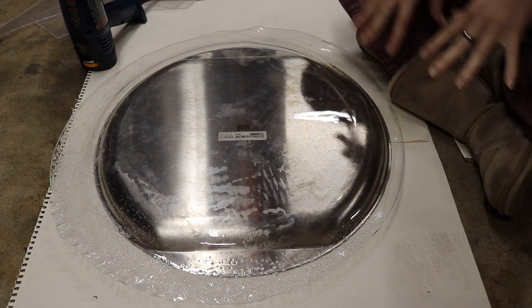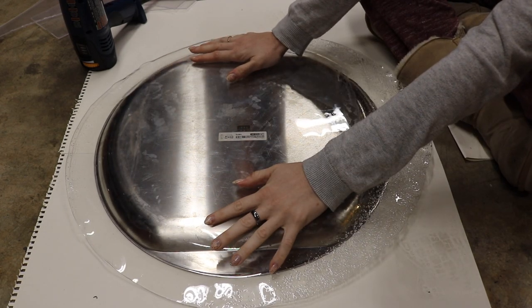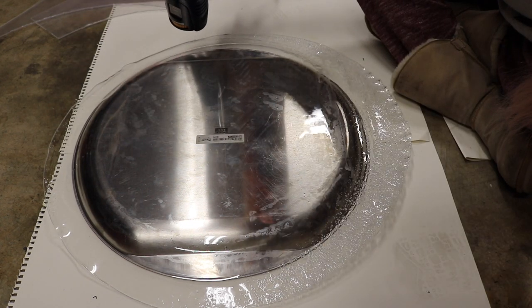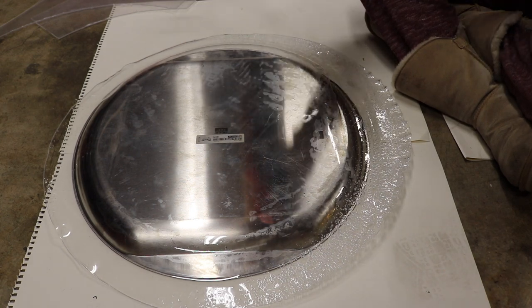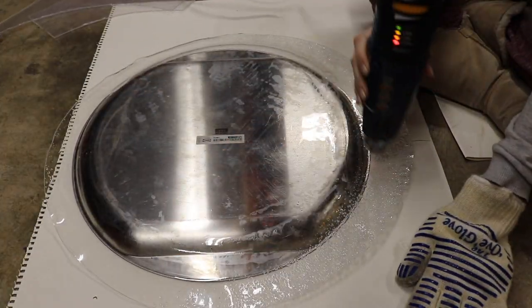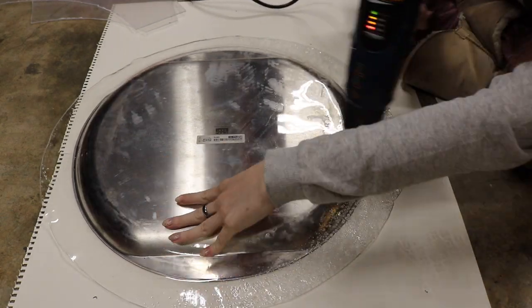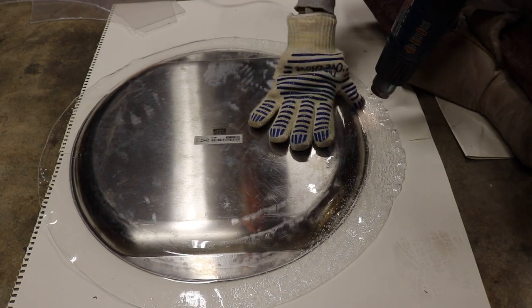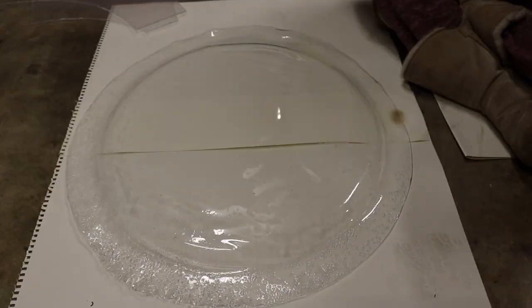I've learned a lot after making this shield and I'm gonna give you some advice. What I did was put my cut piece of plexiglass into the oven on top of my metal heating tray. If you're worried about toxic fumes I would not recommend doing this — heating up any sort of plastic, whether in the oven or with a heat gun, does release toxic fumes. But I rarely use my oven for cooking so I wasn't worried. Putting it in the oven is how I got the basic shape, though my oven was actually too hot and that's why it got all bubbly on one side. If you don't want to use the oven, a heat gun works pretty okay — it just takes a lot longer. I need to reheat the flat areas of my serving dish mold to make them round, so just take the heat gun on a very high setting and let the plastic heat up and melt over the metal shape. You can use this technique for the entire shield without putting it in the oven; it just takes a really long time.